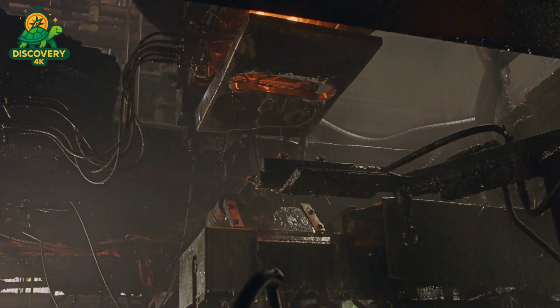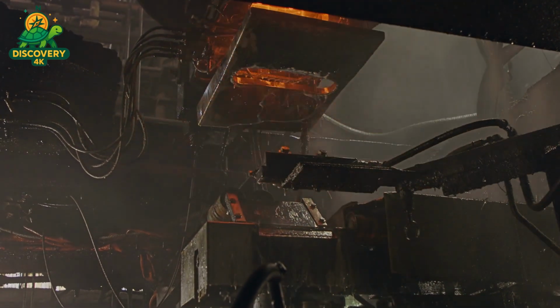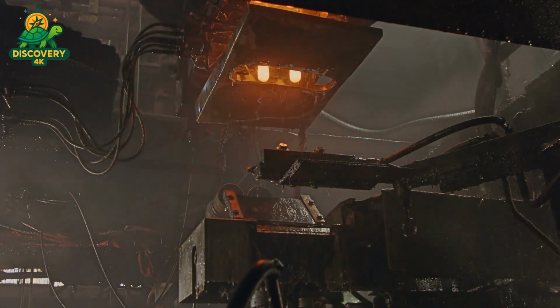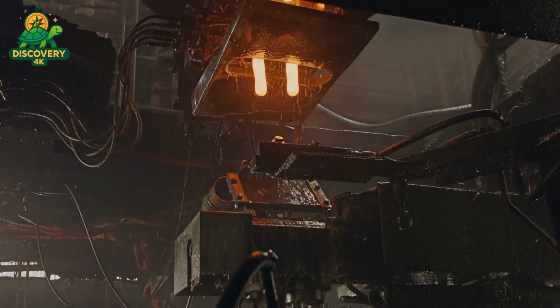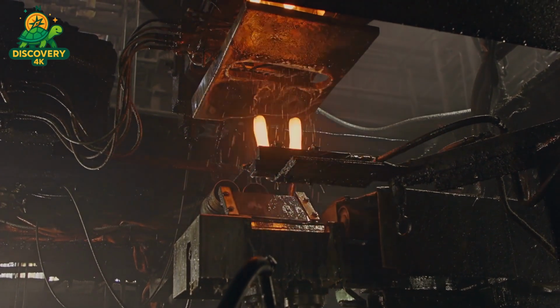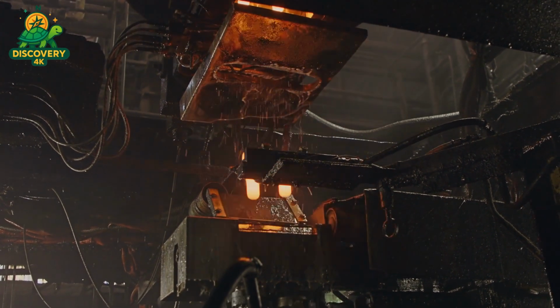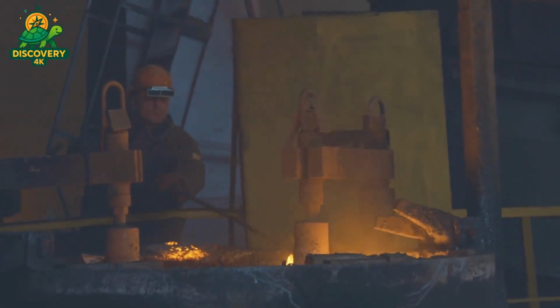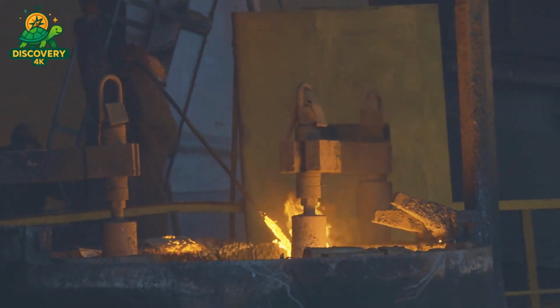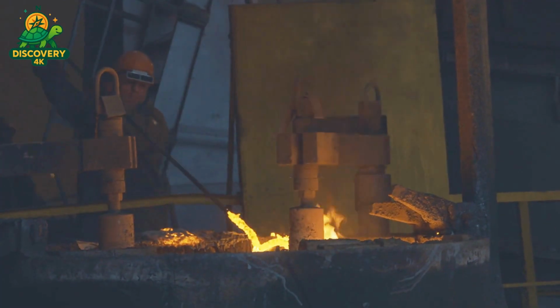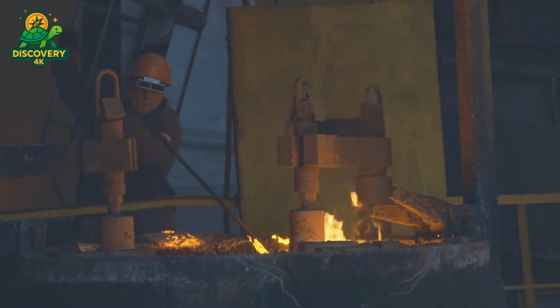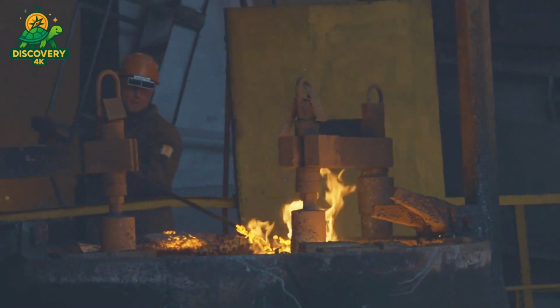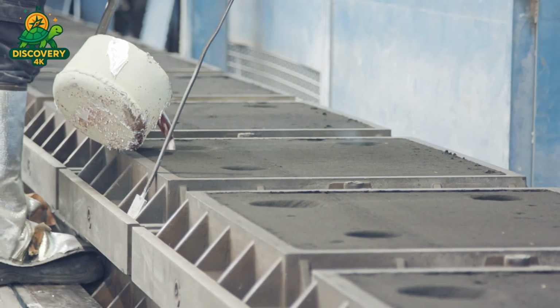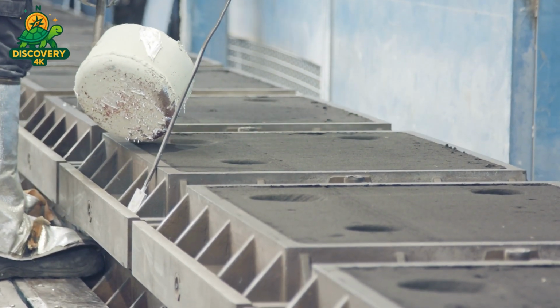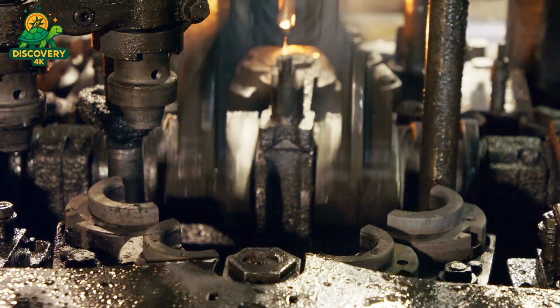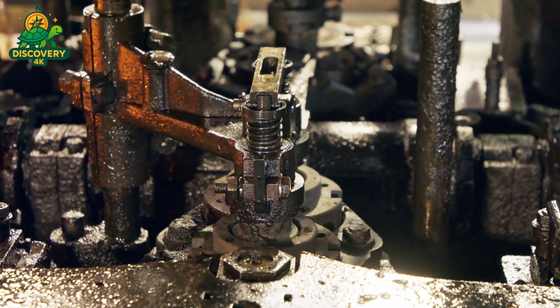But under a microscope, this brown sludge reveals its true nature. Microscopic flakes of gold, some as small as 1 micron across. These flakes cluster together to form what is known in the industry as gold mud. The gold mud is collected, washed with water and diluted acid to remove any remaining chemicals, and then dried in industrial ovens. At this point, it contains over 95% gold by weight, but it's still not pure. The next step, refining and smelting, will take this muddy powder and transform it into glittering bars of 24-karat gold.